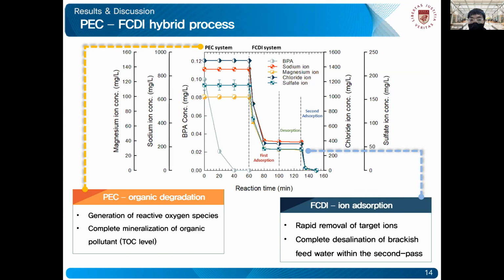As you can see, the aim of our research was to remove both the organics and the ions to generate a potable freshwater standard solution. So that's why, using just an oxidation process, we would be able to remove the organics, but then we would need a subsequent process to remove the ions.